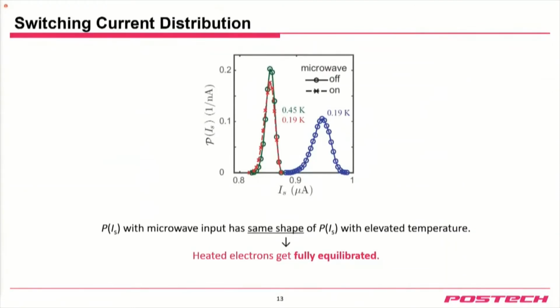Okay, so this is the switching current distribution. When we have no microwave at the base temperature, this has the highest supercurrent. The supercurrent has some switching distribution. When we keep the base temperature and shine the microwave, the IC decreases and the distribution changes, something like this. Whereas if we don't shine the microwave, but only increase the bath temperature, increasing the electron temperature up to 0.45 Kelvin, we can make the current distribution almost identical. That means the decrease of switching current by shining microwave is really due to the increase of the electron temperature, because the shape is almost identical.